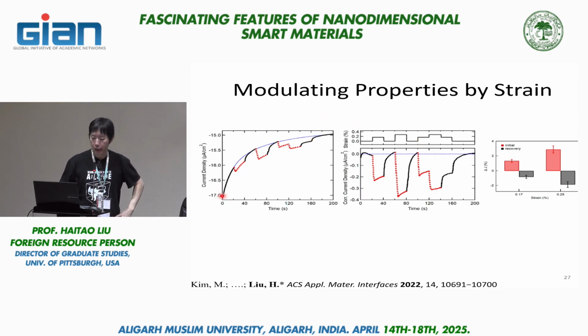This is the raw data. The electrochemical current decays over time, probably because of surface contamination. I don't know exactly what. But on top of that, when we apply the strain, we see this periodic drift. So if we get rid of the background, we get something like this, which is easier to analyze. What you see here is when we apply strain, we find this enhancement of electrochemical current. And when we release the strain, it reverses back. And overall, we see this very positive correlation between the amount of strain and the kind of current modulation we see in the electrochemistry.